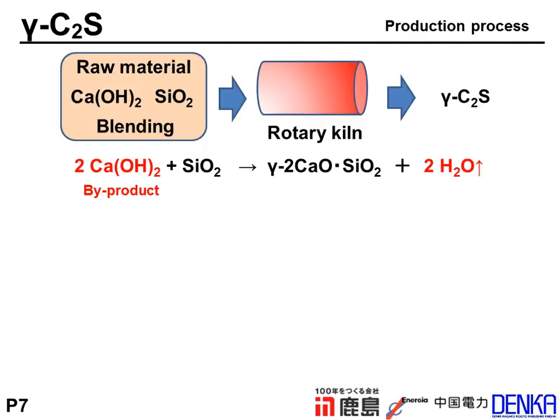The production process of gamma C2S is below. We use calcium hydroxide and silicon dioxide as raw materials, and they are blended in a theoretical molar ratio and fed into a rotary kiln. Then in the rotary kiln, they are calcined at over 1400 degrees Celsius and changed into gamma type dicalcium silicate.